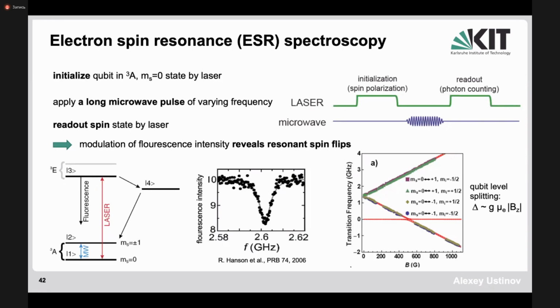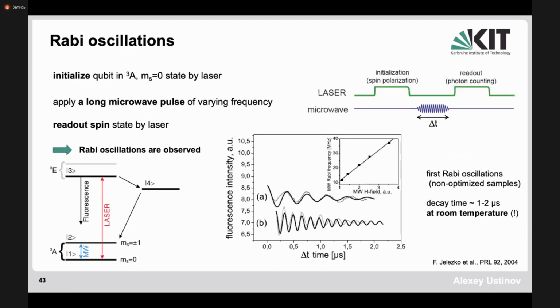And this shows the line which is observed in the bulk ensemble of the NV centers, and this shows also the energy splitting depending on magnetic field, which shows the spin states associated with this kind of defect. So one can measure, of course, Rabi oscillations there and increase the intensity of the microwave field. You see this intensity of microwave field is increased, and then the Rabi frequency increases. So this low frequency is A and high frequency is B.